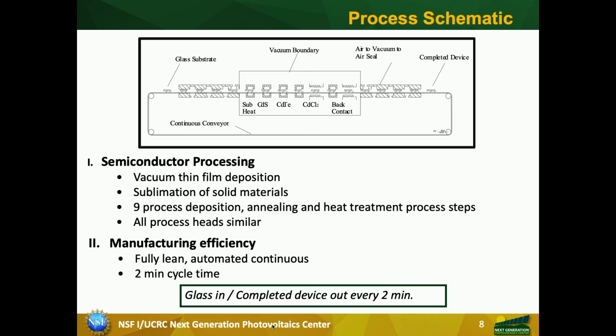And you can see how this manufacturing happens. This was a system we had in the lab, and that was commercialized by Abound Solar. It's a sheet metal belt made of Inconel that goes around like this. And we cut pieces of the fluorinated tin oxide material and put it in. And we have a tunnel which is partially pumped, and the glass would come in. And there are 9 process stations. They are all identical hardware. This is graphite heated by lamps that vaporize the material and deposit.